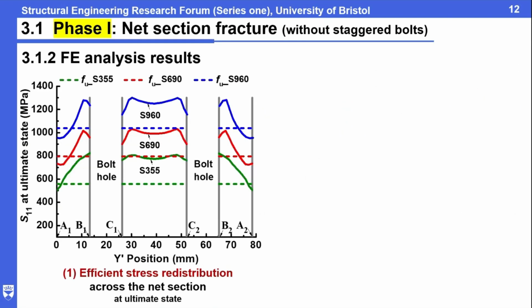So this is the first finding based on the numerical analysis. We plot the stress development distribution across the critical net section. The dotted line is the Fu level of each material. We can see that the stress distribution at the ultimate state is already fully developed. Even the mild steel is much higher than Fu. For the high strength steel it is above, and at the minor error it is lower, but the average is above already. So that's why we can achieve the ANFU.